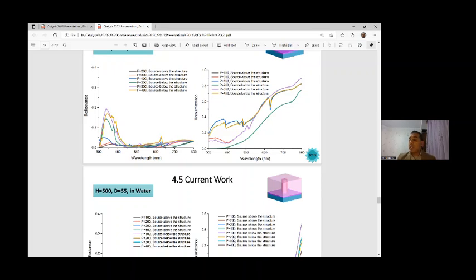But in structure 3, the results show that the reflectance is higher when the source is above, and the transmittance is the same in both cases. Therefore, it can be said that the reflectance due to the perovskite is more. This is the impact of utilizing the perovskite material in the system. Here the importance of the perovskite structure is evident for us. So the absorption on the perovskite side is less compared to the TiO2 in structure 3.